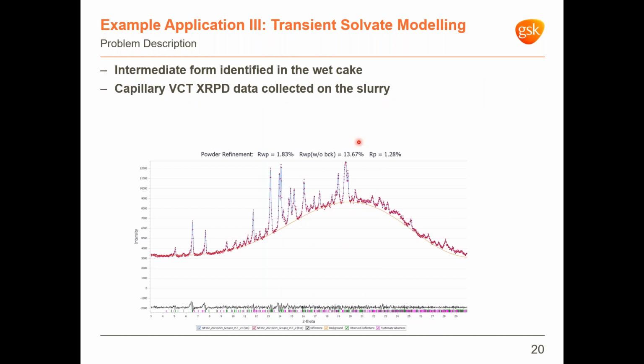And this is an example where we have recently applied this workflow. The intermediate form rapidly desolvating to yield the target API development form was observed and characterized in the wet cake. And in order to try and gain some structural mechanistic understanding on the drying process, we collected variable counting time XRPD capillary data, sealing the slurry in a capillary for data collection.